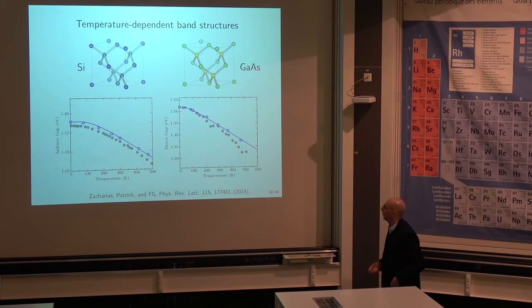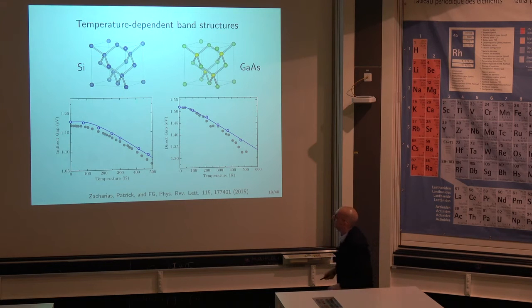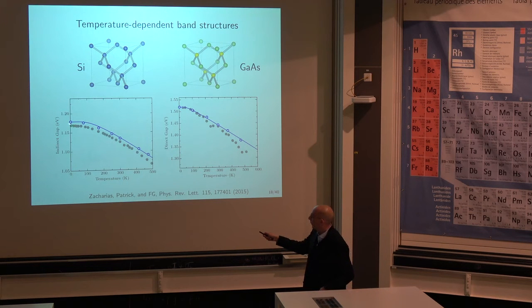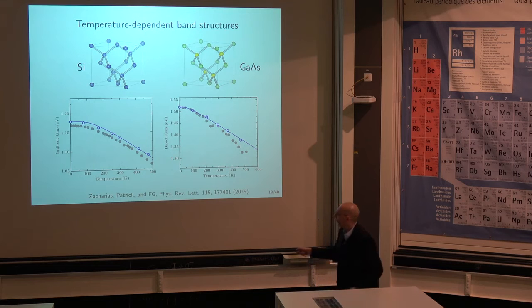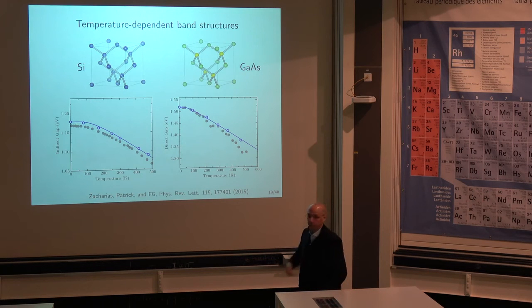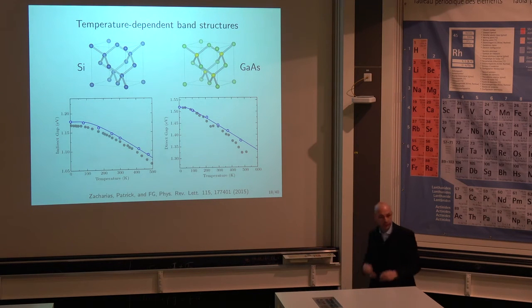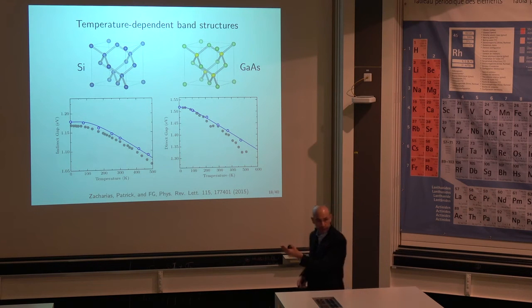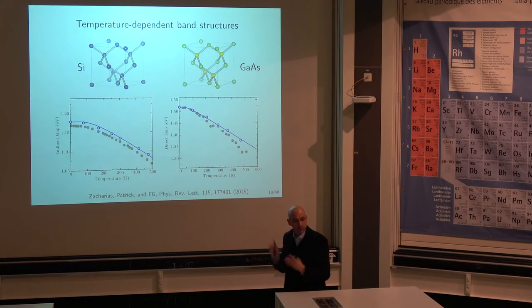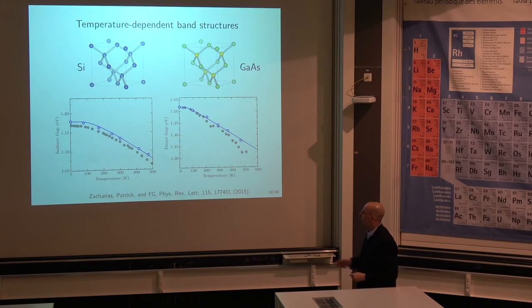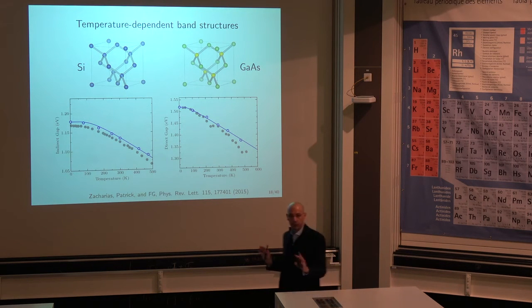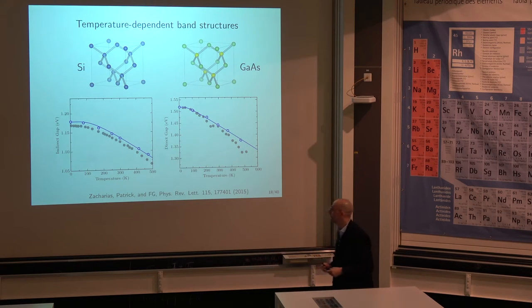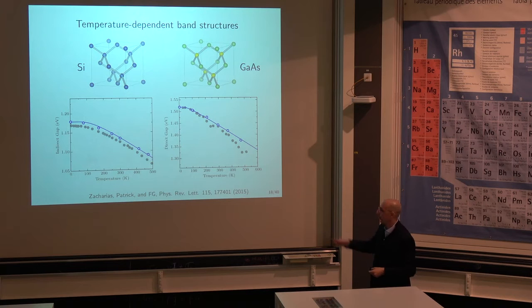So let me show you a couple of examples. So this is basically standard silicon in the diamond lattice. And what you can see basically is the measurement of the band gap. This is ellipsometry as a function of temperature. And these are our ab initio calculations. So they're not perfect, obviously, because we have problems with correlations in density functional theory. So we had to do some GW corrections, which are not accurate to, let's say, 5 millivolts. But the result is quite good, apart from the offset. And I would like to emphasize that these dots, the blue ones, have absolutely no empirical parameters, okay? So we're not fudging anything. This is basically what comes out of a straight calculation. And you see that basically they follow the experiments quite nicely.